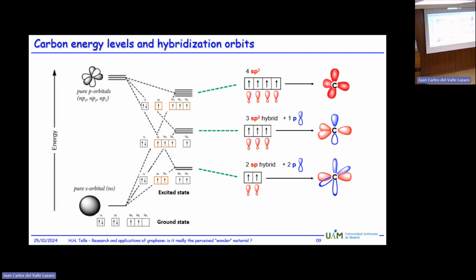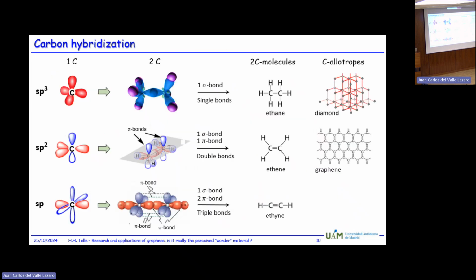So this on its own does not tell you very much, but you have to go for the situation that you bond actually these atoms together. And if you bond carbons in its sp configurations, for example, the lowest one, which is 2 carbon atoms, then you actually have 1 sigma bond and 2 pi bonds. So it's a triple bond, which we all know, for example, in the molecule ethyne. If you go one step up to a sp2 configuration, then you have 1 sigma and 1 pi bond, and you have a double bond, which, for example, is the simplest hydrocarbon molecule, ethene. And you go up to the final stage, the sp3, then you have a single sigma bond, and you end up with ethane.